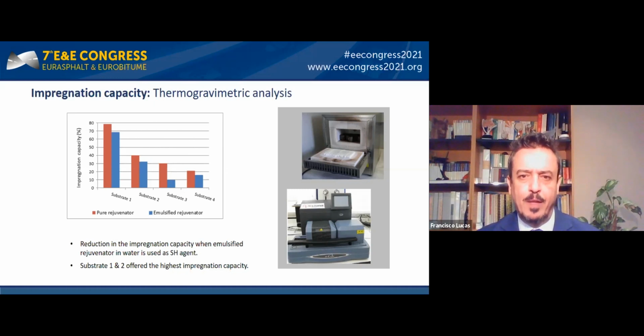Since the encapsulation method was vacuum impregnation, in the research project, we have studied the phenomenon using thermogravimetric analysis. In it, four different substrates have been considered, and we have analyzed the impregnation capacity on the pure and emulsified regenerating agent. We can see how there is a reduction in the impregnation capacity in the rejuvenator that's provided via emulsion. Likewise, we observe how the substrates that we have called 1 and 2 have the highest impregnation capacity.